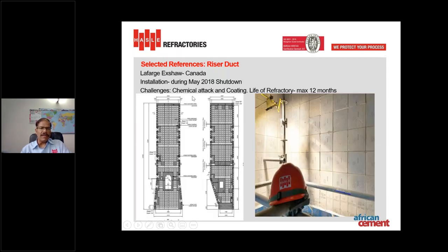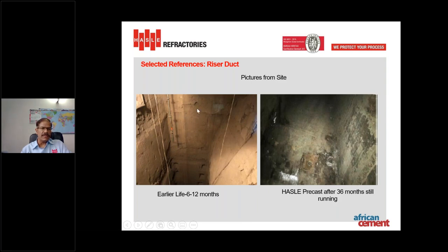This is the case of a Lafarge plant from Canada. Actually, they were facing a lot of chemical attack and coating issues in their riser area, and they never achieved a life of 12 months. We studied the process, and we checked the site, and we saw that their refractory was very much damaged because of chemical attack, and we did our modular lining in the whole riser area. And this is the picture.